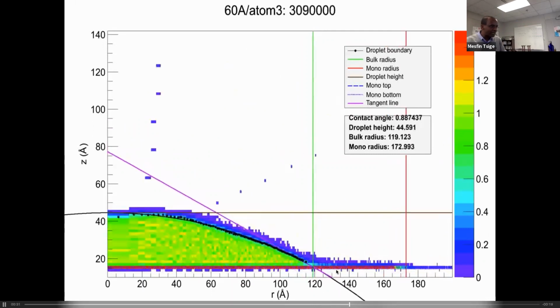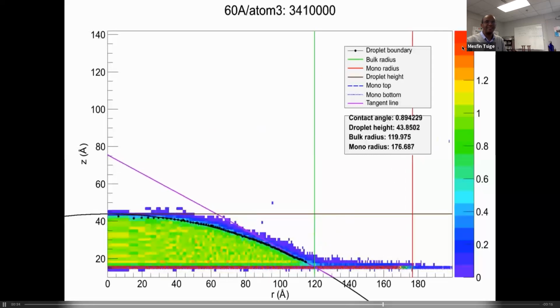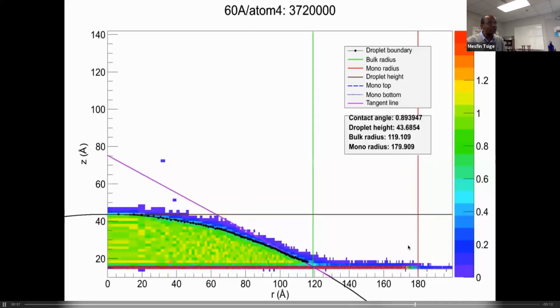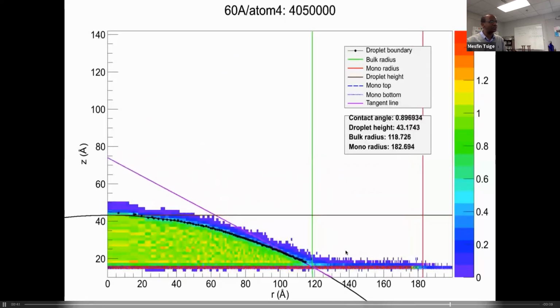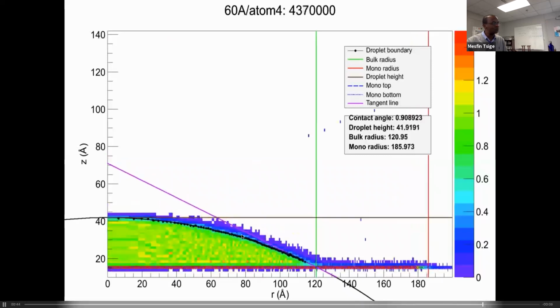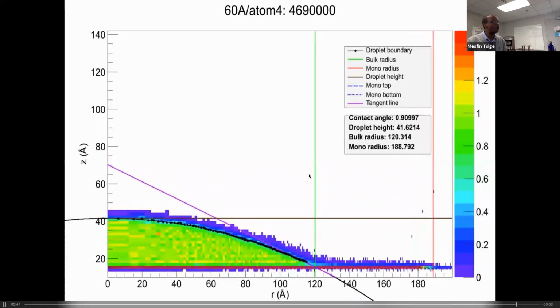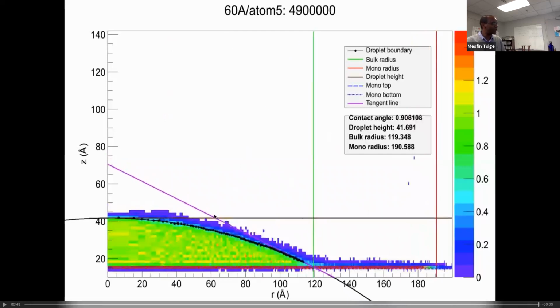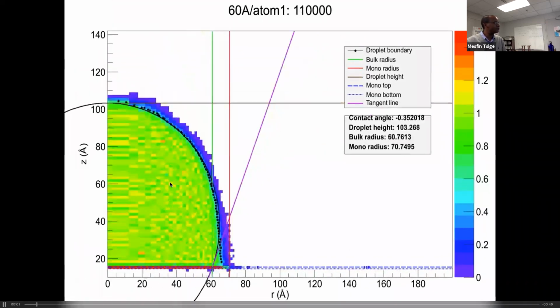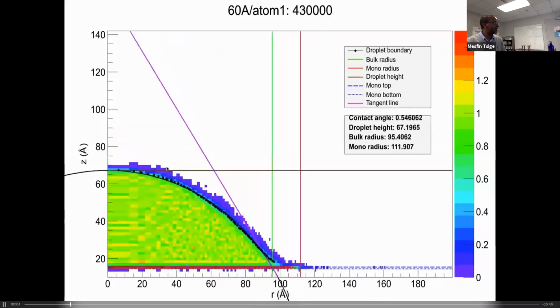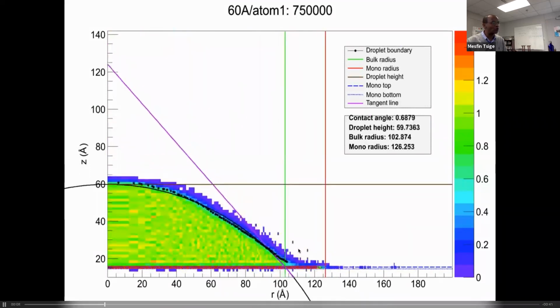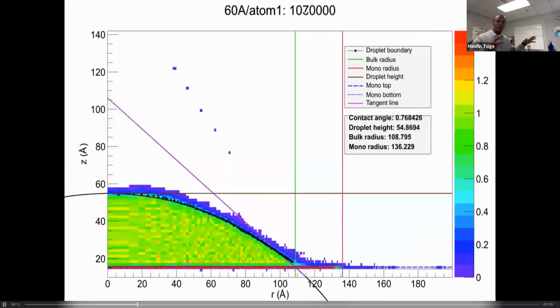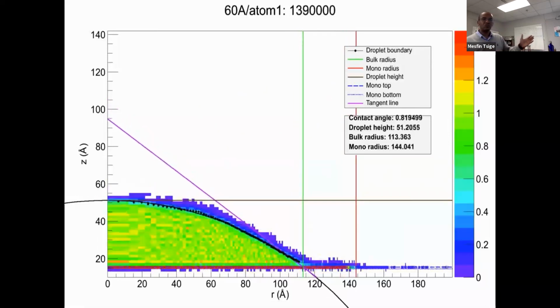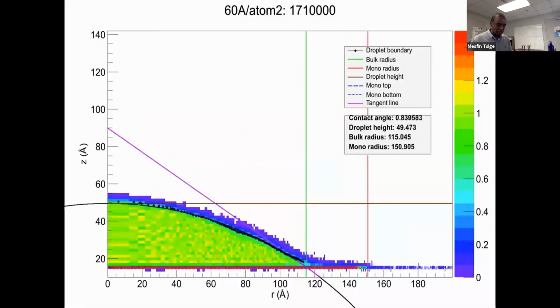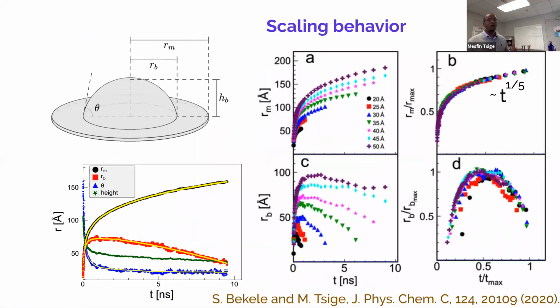But the two areas to look at are this red high density region, that's a monolayer, and that monolayer is changing. In our case, we monitor its position. And we also have this hemispherical cap, which is also changing. We monitor that with the green line. We also monitor the contact angle. So if I play this one again, the contact angle is changing, the height of the droplet is changing, the location of both monolayer and the hemispherical cap, all those quantities are changing over time. So we look at how all those things change with time.